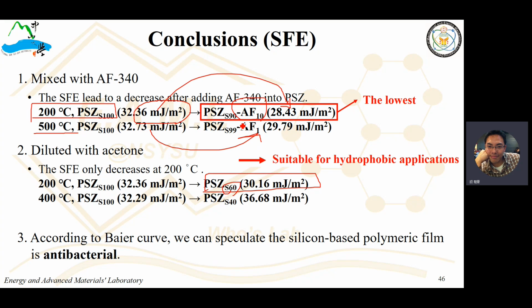Then we can find that the sample of the precursor incorporated with 10% fluorinated resin has the lowest surface energy for this dual functional coating, anti-corrosion, antibacterial, or anti-fouling. If you just want to focus on the hydrophobic application, maybe you just dilute with acetone and you can get the highest contact angle. According to the Baier curve, we can speculate that the silicon-based polymeric film is antibacterial.